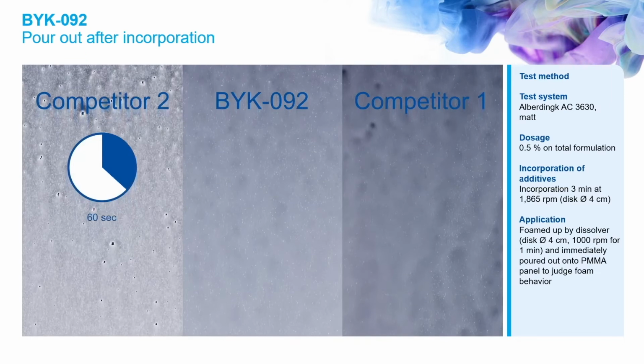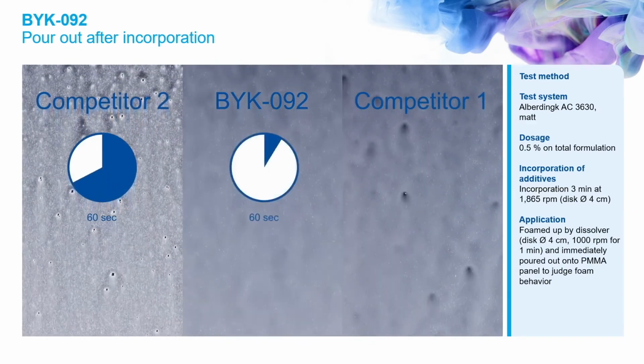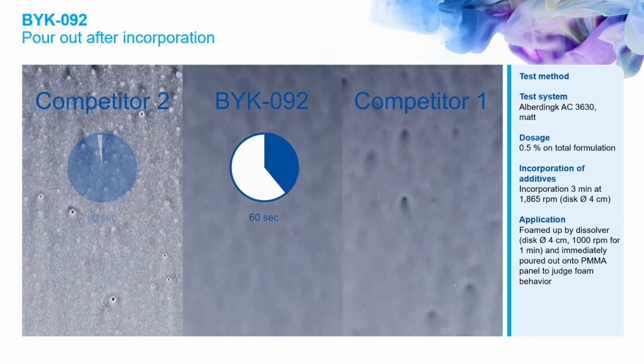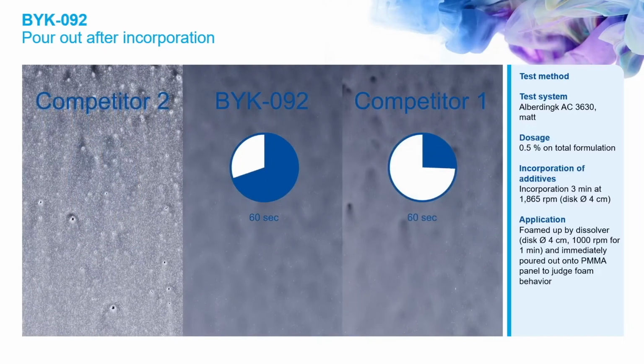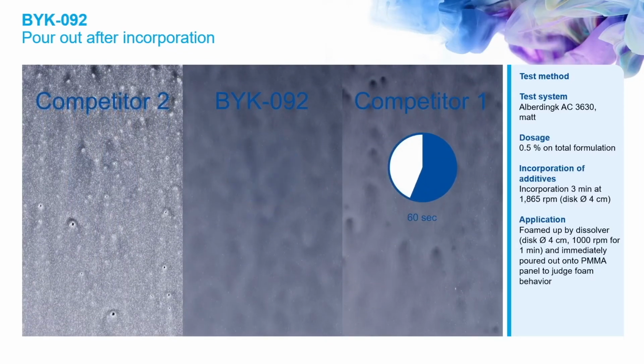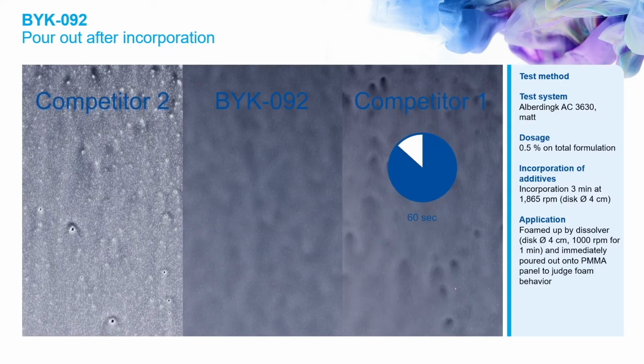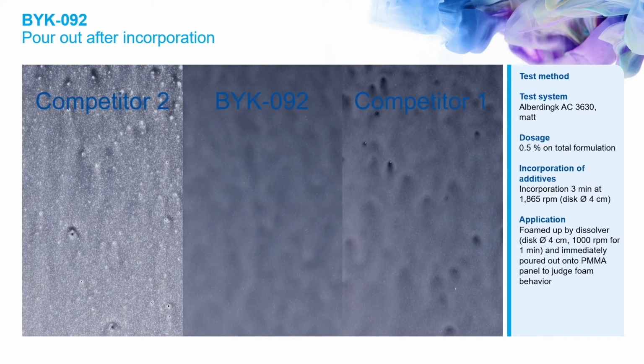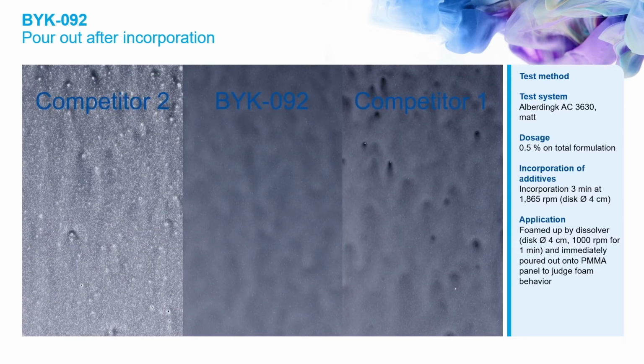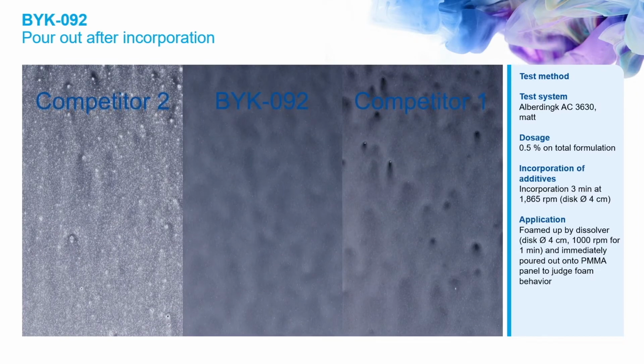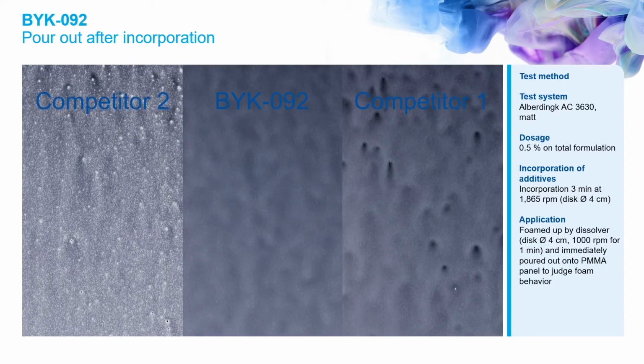So if you just wait the minute and then you take a look, on the left-hand side, we have our competitor 2, which is a market standard, and there you see that it has a lot of foam left, so maybe it's a bit too compatible. In the middle, we have the BYK 092, which has no foam left and really a flawless surface, so really nice result. While on the right-hand side, the defoamer is really active, so you can see no foam, but you see some surface defects, so maybe it is a bit too incompatible.